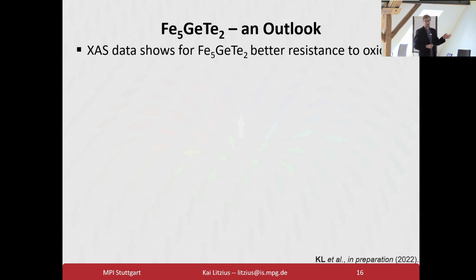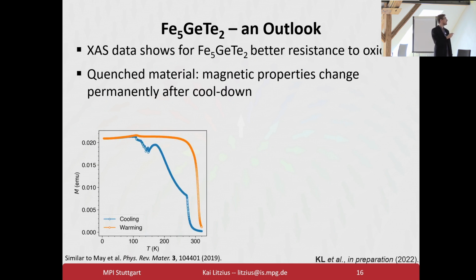This material is also comparably stable versus oxidation, which is in general, of course, a problem once you deal with monolayer thicknesses of the system, because if you have iron in the system and you've got a monolayer of it, it does not really like to come in contact with any kind of air. So here we've got the saturation magnetization versus temperature of one of the quenched flakes. What you see in blue is the cooling cycle coming down from the quenched as-grown part. And you see that it increases, and something funny happens a bit above 100 Kelvin. Then you cool below 100 Kelvin, it comes back, and it follows a different loop.